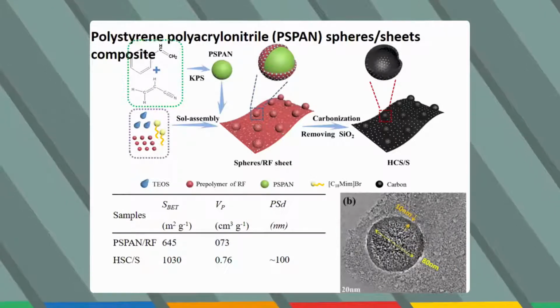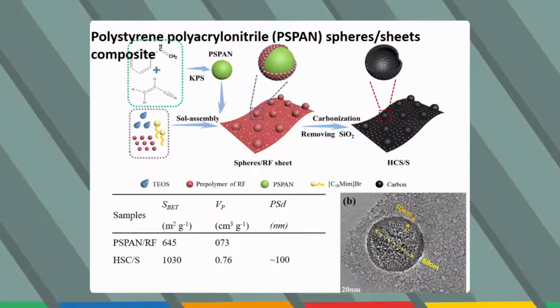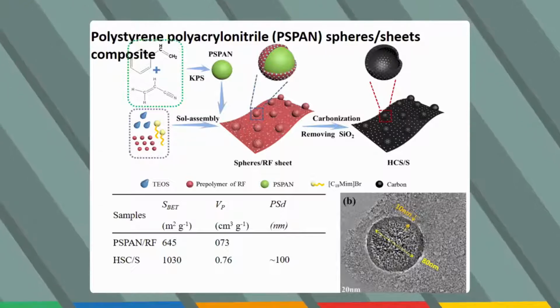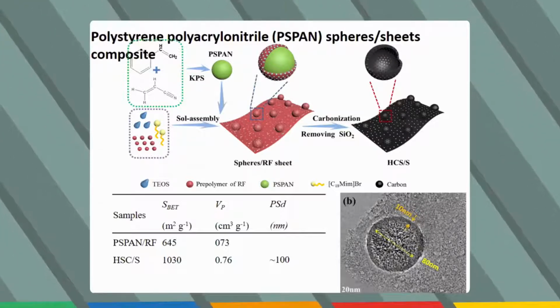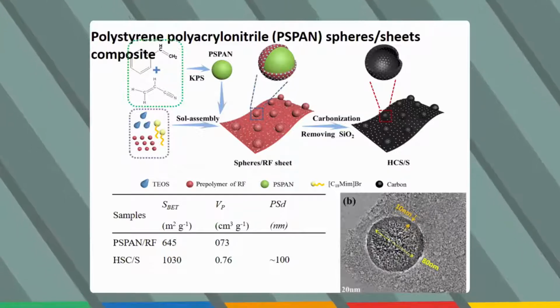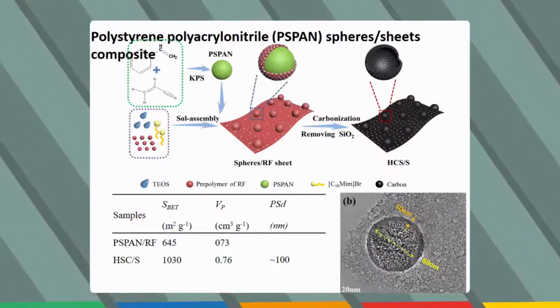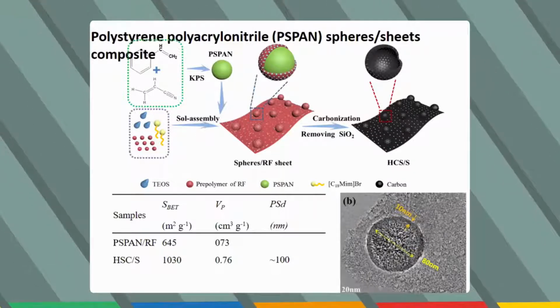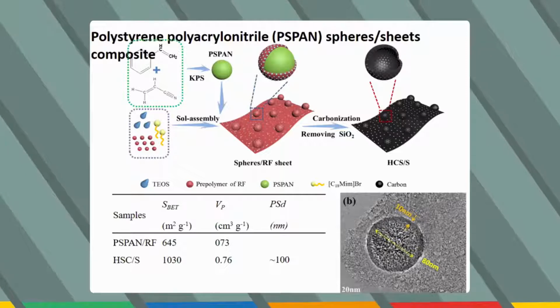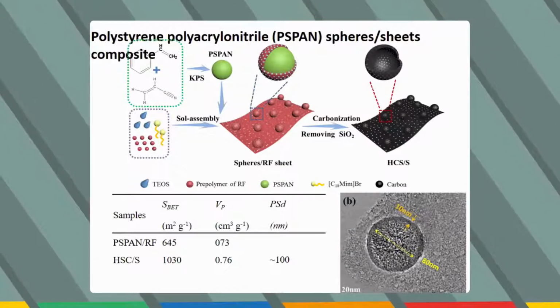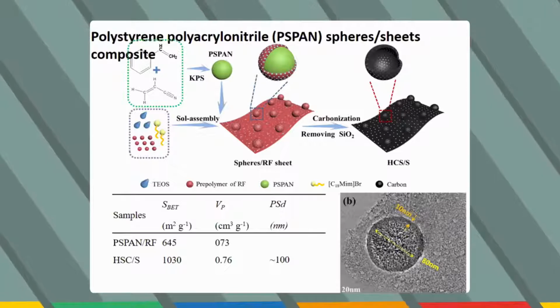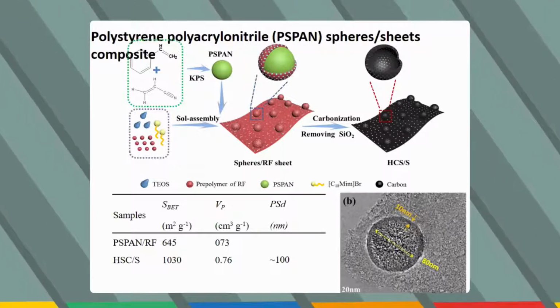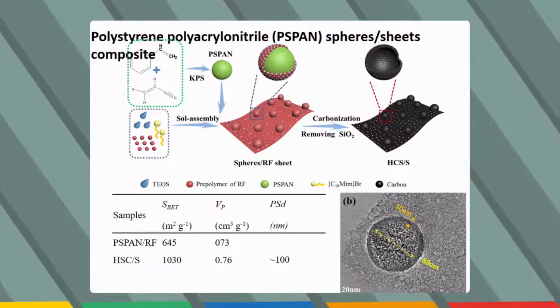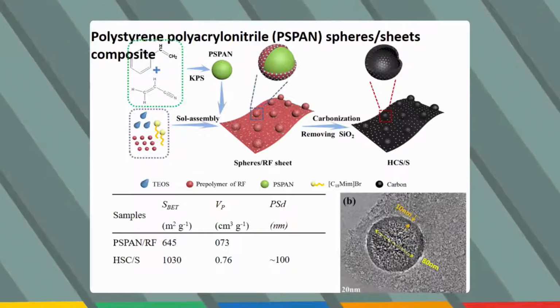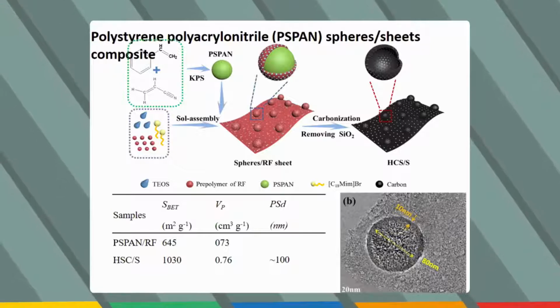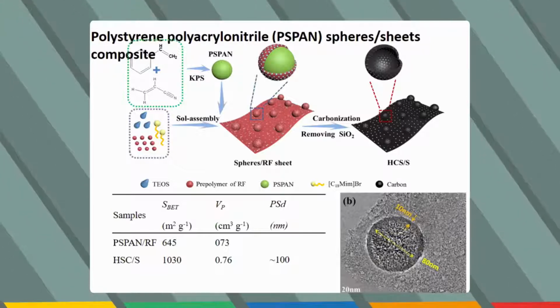Another method that we used was the polystyrene-polyacrylonitrile. In this method, we took the PS-PAN resin and assembled it on a flat carbon sheet to form the carbon spheres on the surface of the carbon sheet. You can see the surface areas were also very good. And on the right, we can see the carbon sphere with an inner diameter of 80 nanometers and a shell thickness of 10 nanometers on the surface of the carbon sheet.